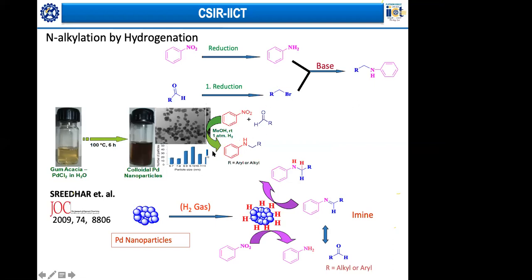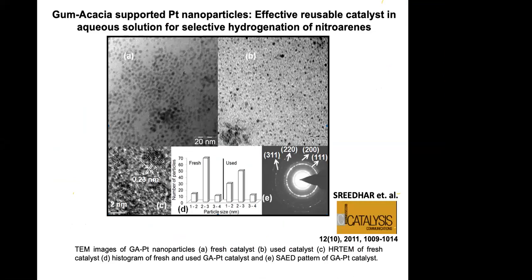At room temperature, with just a hydrogen balloon attached to it and methanol as an organic solvent, you can get the desired product. Then we tried to work on platinum, because platinum is another interesting substance, and here it was still more interesting in the sense the size of the particle is between 2 to 3 nanometers. That was 8 to 10 nanometers, and even at that scale, you can very clearly see the platinum nanoparticle lattice spacing.